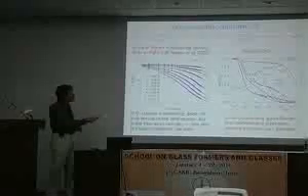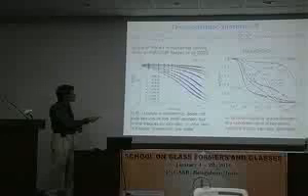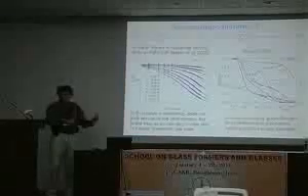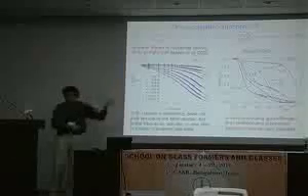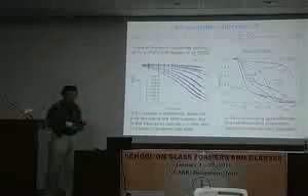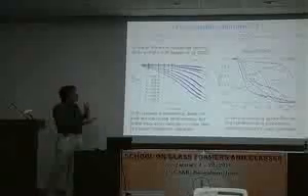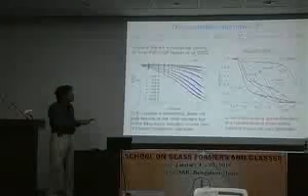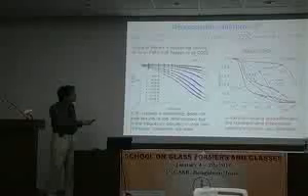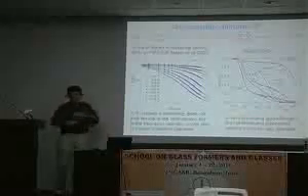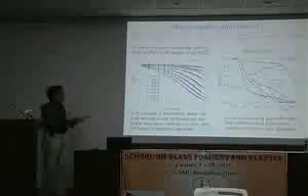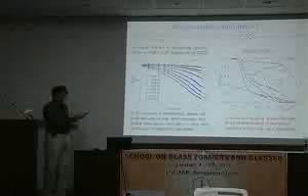If you multiply something finite by a Q vector that is very large, this becomes huge, and the exponential of something huge is random, and therefore these functions decay very quickly to 0. The only thing that survives is the diagonal term, j equals k.